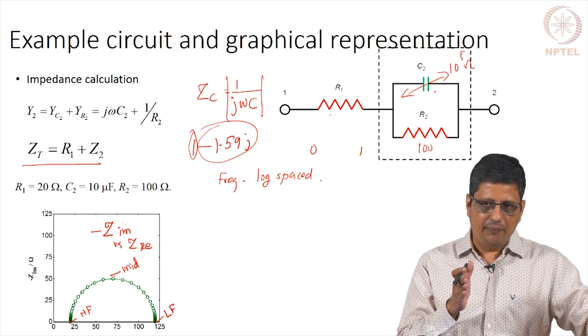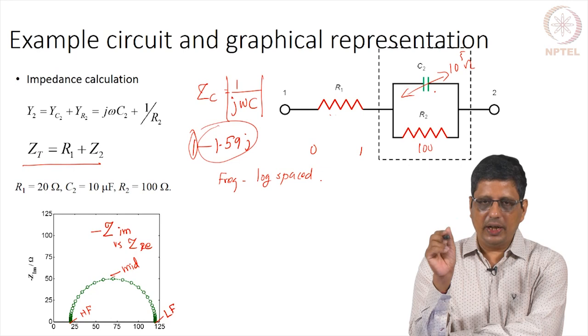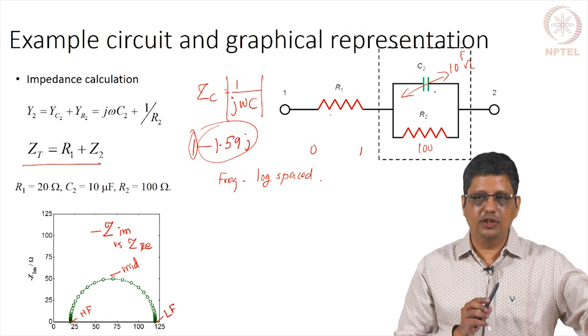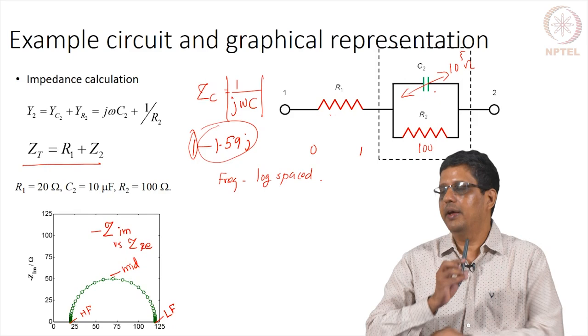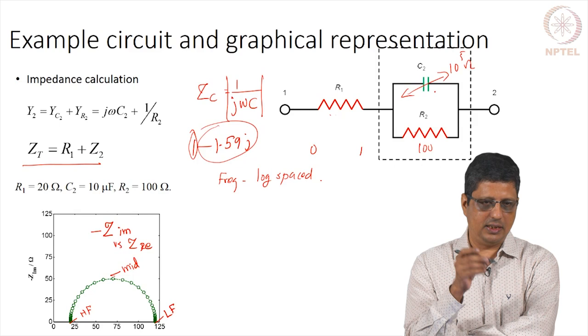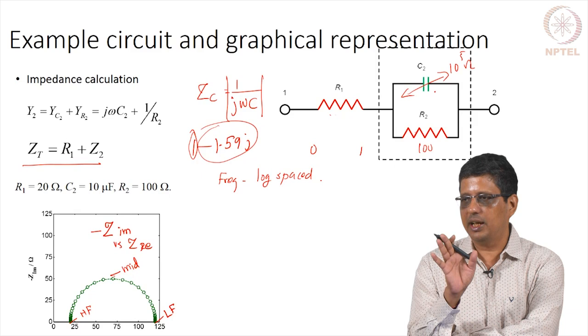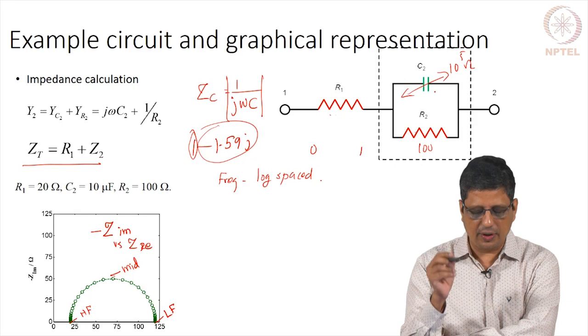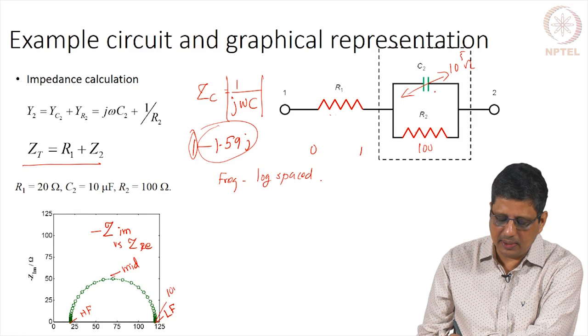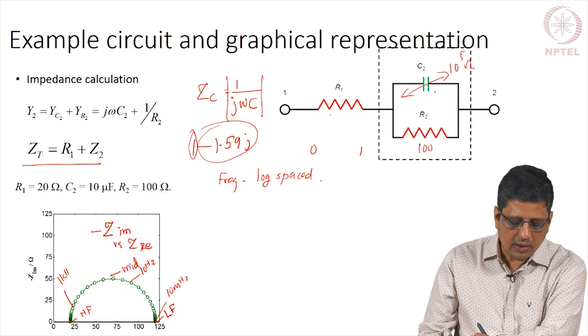I will reach 10, then multiplying again it goes in a geometric series, covering from 1 to 10 in for example 6 or 7 intervals. So I say 7 frequencies per decade or 6 frequencies per decade. For example: 1, 2, 4, 8, 10, then 20, 40, 80, 100. We do not like to take harmonics — I do not want to take integer multiples of the base frequency. We want to take 5, 6, or 7 frequencies per decade. More frequencies per decade gives better resolution but takes longer time. When you present the data, you must mark which point corresponds to which frequency — e.g., 10 millihertz, 10 hertz, 1 kilohertz.